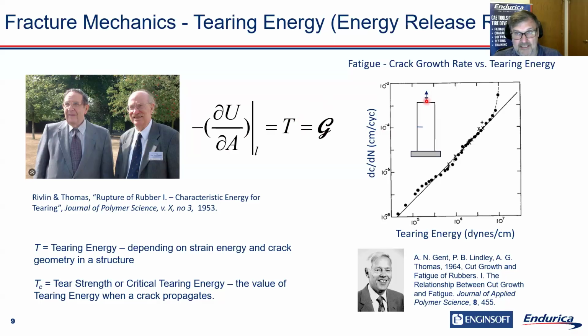So if you think about holding a specimen like this, or deforming it very slowly with a fixed displacement, at some point that crack will move a slight amount. When the crack moves, the total energy in the specimen is going to go down because the crack has made the total structure more compliant. So the total strain energy goes down as the crack increases by an amount delta A. The amount that energy goes down divided by the crack area change, delta A, is this quantity, tearing energy or energy release rate.